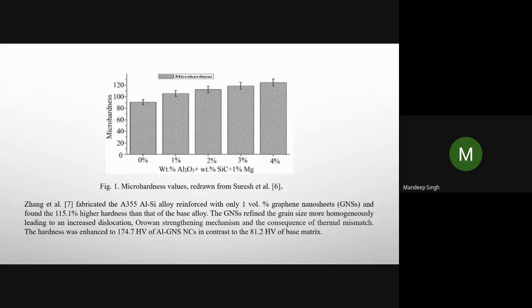Then next, Zhang and others fabricated the A355 aluminum silicon alloy reinforced with 1 volume percent of graphene nanosheets and found 115.1% higher hardness than that of the base alloy. The graphene nanosheets refined the grain size more homogeneously, leading to an increased dislocation, Orowan strengthening mechanism, and the consequence of thermal mismatch. The hardness was enhanced to 174 Vickers hardness for the aluminium graphene nanosheets nanocomposite in contrast to the 81.2 Vickers hardness of the base matrix.